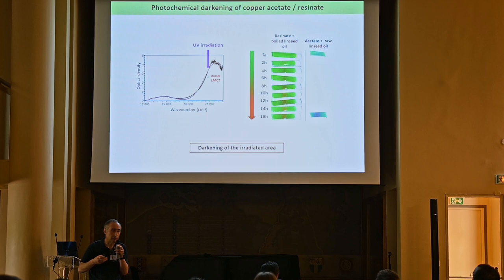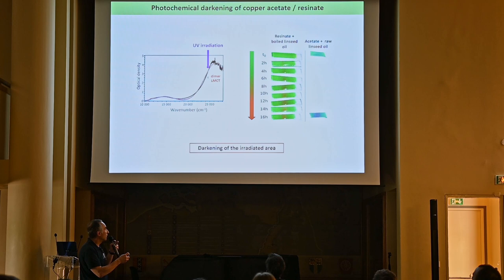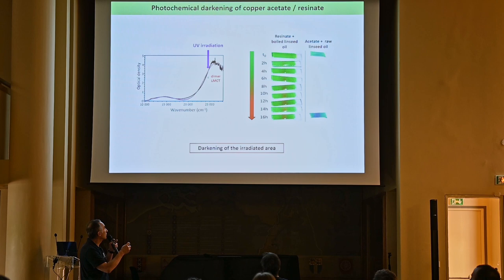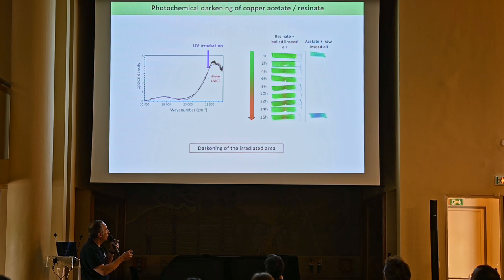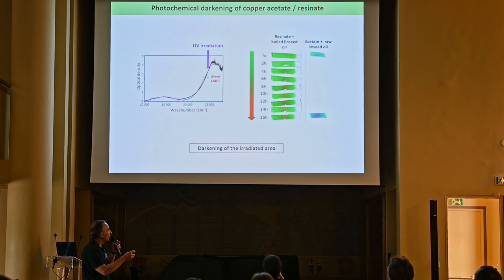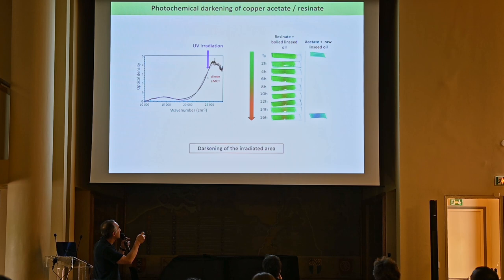Now we move to what happens when the pigment mixed with oil interacts with light. We prepared samples of resinate with boiled oil and acetate with raw linseed oil, and irradiated with UV light specifically within the dimer ligand-to-metal charge transfer absorption band. With increasing irradiation time, a brown spot grows at the irradiated point in both cases — we can reproduce the darkening of the pigment by irradiation specifically in this dimer absorption band.